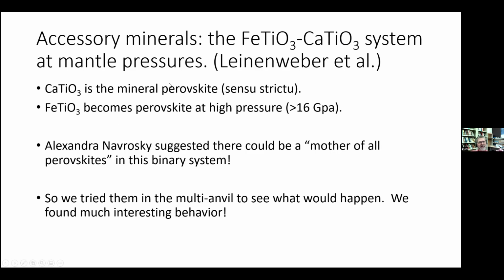And it started with work on FeTiO3, where Syono had discovered the lithium niobate or corundum phase. He called it corundum, but it's actually lithium niobate. But it turns out it's perovskite at high pressure, and that's work I did at Tokyo University to look at that in a diamond cell and find out that this is actually perovskite at high pressure. So we thought, well, Alex Navrotsky was thinking calcium, iron, maybe if we reacted them together, we could get the mother of all perovskites, is what she called it, which I thought was a funny term.